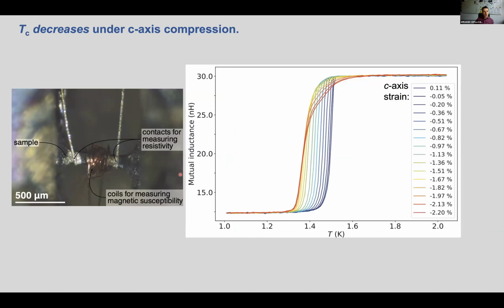So this is what the experiment looks like. Here's our sample of strontium ruthenate. This is the c-axis. It has been shaped so that we reach very high stresses, and then we wrap coils around it to measure the magnetic susceptibility. I show you raw data here. This is the superconducting transition as we compress the sample.